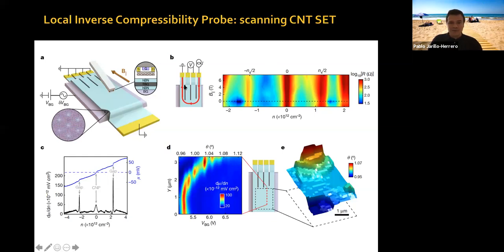But you can measure here the resistance versus magnetic field. And I should say that in his scanning setup, the magnetic field is parallel to the graphene plane. He doesn't have perpendicular magnetic field for that initial experiment. So if you measure resistivity versus parallel magnetic field, you can see this is the Dirac point. This is the insulator state at 2 electrons and 2 holes per moiré unit cell.